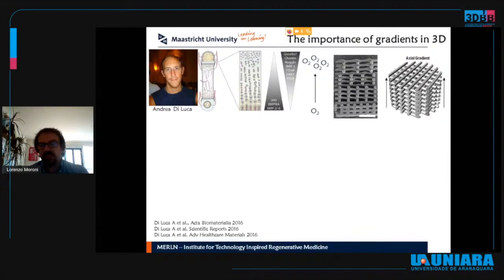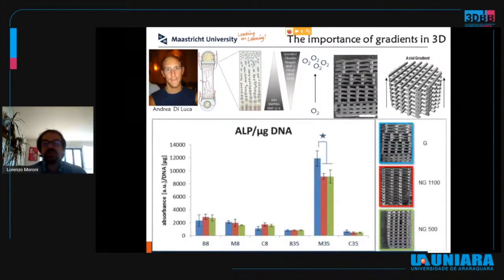So layer by layer, you can choose at a predefined layer to change the size of the pores, as depicted by the scanning electron microscopy on the top right of the slide. And we have done that trying to approximate biological principles as much as we could. If you think about skeletal tissues, typically an osteochondral defect, where you have both articular cartilage as well as the subchondral bone underneath, you would have gradients of many different biological factors, among which gradients of oxygen, where typically you would have low oxygen closer to the cartilage side and higher oxygen closer to the bony side of such an osteochondral scaffold. So we created such a pore size gradient axially through the scaffold fabrication methodology.